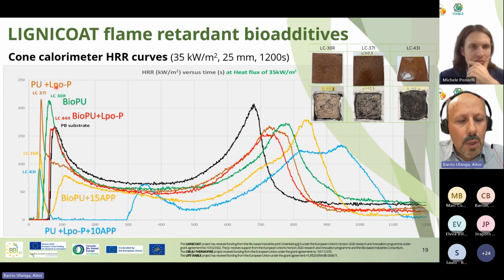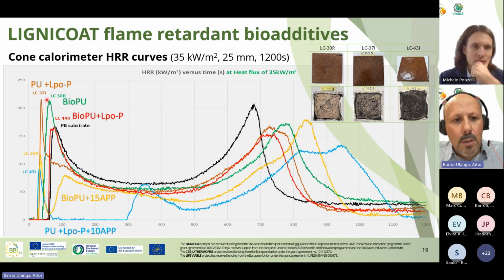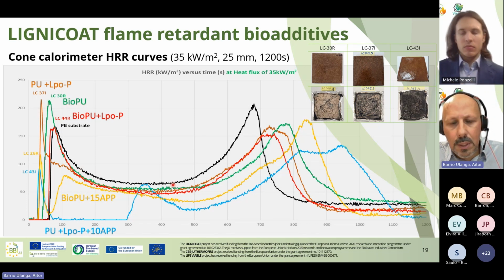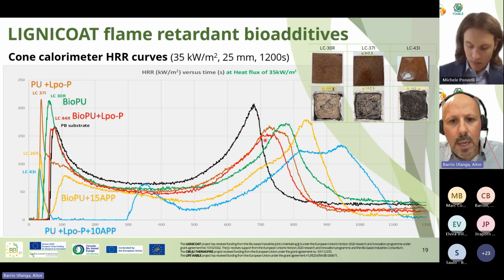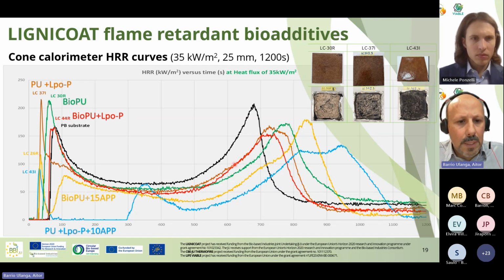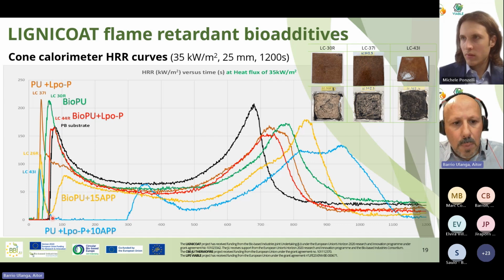With the use of 2.7% of phosphorus in the LPO, phosphorylated LPO, we see the peak similar to the previous, to the bio-based formulation, but we decrease significantly the combustion of the material. But the most interesting result is the synergy effect between 10%, just 10%, and the LPO. So we have a low peak, an important barrier.